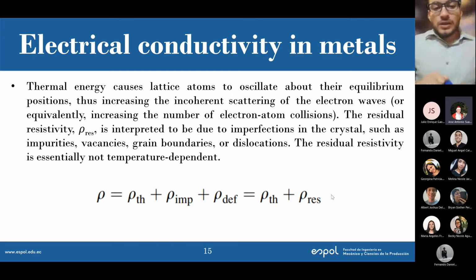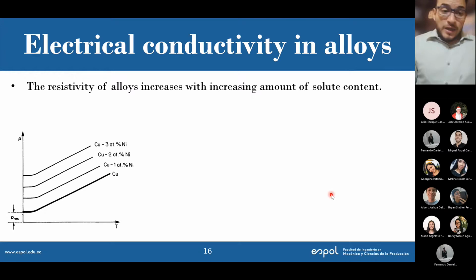Yeah, there will definitely be an effect of solute atoms. And actually, the resistivity of alloys increases with increasing amount of solute content. For example, you see copper there. If I put 1 atom percent of nickel in that copper, I see that the resistivity increases. And remember, if your resistivity increases, conductivity is decreasing. If I put 2 atom percent of nickel, resistivity increases even further. If I put 3, even more, and I can keep adding more and more nickel. Obviously there is a limit, but I can keep increasing the nickel content and I will have a higher resistivity.